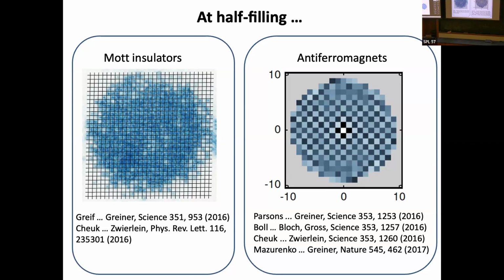So this can all be quantitatively compared to results from quantum Monte Carlo, where I said at half filling, things can be calculated very accurately. And there's very good quantitative agreement. You usually have to leave the temperature as a fit parameter. So that allows us to actually extract thermometry on these systems by fitting to the data from quantum Monte Carlo. And this gives us an idea of the temperature of the systems. It's typically, we can get to temperatures in the best case, about 15% of the tunneling energy scale.